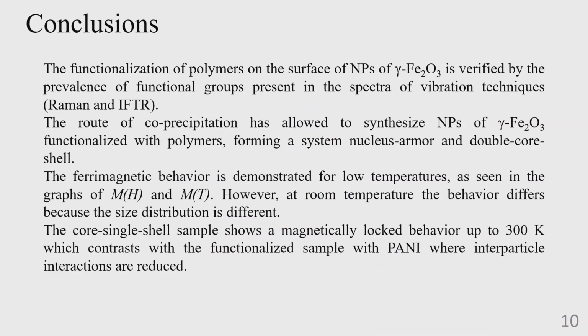Well, so the conclusion: finally, the functionalization with polymers of the surface of the maghemite nanoparticles is verified by the prevalence of functional groups present in the spectra of vibrational techniques. The first technique, the coprecipitation route, has led to the synthesized nanoparticles, and ferrimagnetic behavior is demonstrated at low temperatures, as seen in the graph of M versus H and M versus T. However, at room temperature it is different because the size distribution is different, as we see in the TEM.